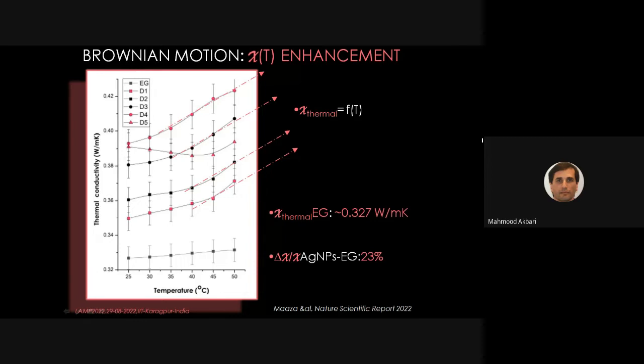But as you can see, colleagues, here, for example, if we take thermoconductivity of silver nanoparticles in ethylene glycol, what happens is that, within the temperature around 20 to 50, at different doses, fluences, the thermoconductivity of the nanoparticles has a tendency to increase faster above 40 degrees Celsius than at low temperature. This is for all the different doses, except the highest dose, the highest fluence. What is sure, colleagues, is that this is likely due to the thermal conductivity due to the Brownian motion.